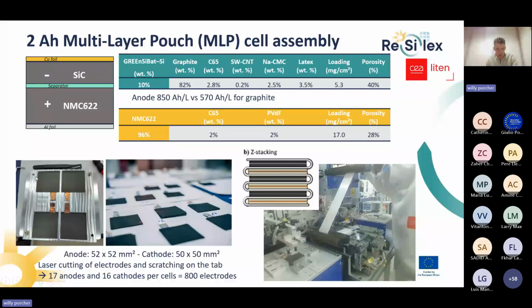So here you see the different anodes and cathodes for 2 ampere hour cells, using anodes of 52 by 52 square millimeter and cathodes of 50 by 50 square millimeter. We need 17 anodes and 16 cathodes. That means for the more than 20 cells that we assembled, more than 800 electrodes. For that, we have a laser cutting process that we use to cut the electrodes, and also to scratch the tabs properly to be able after to collect the current.